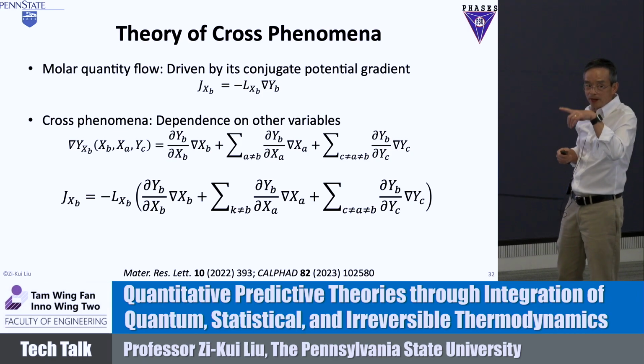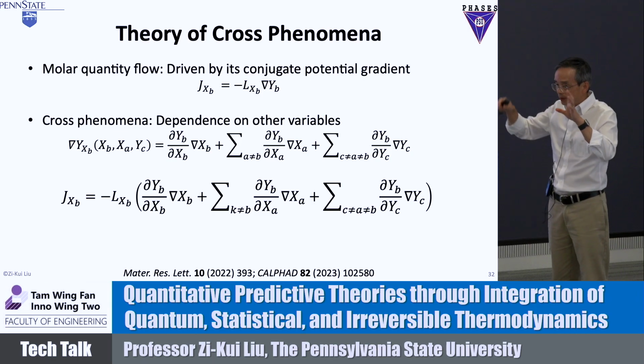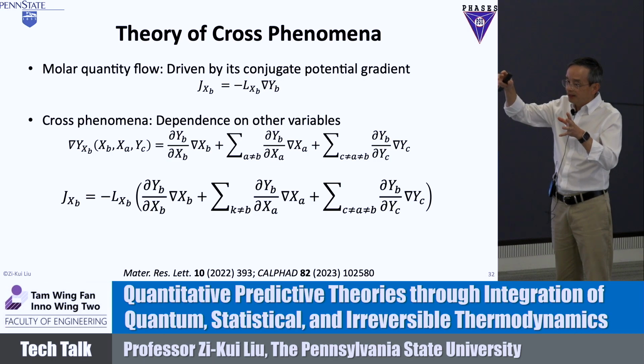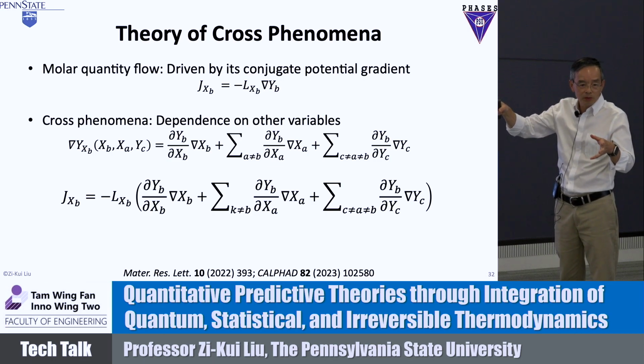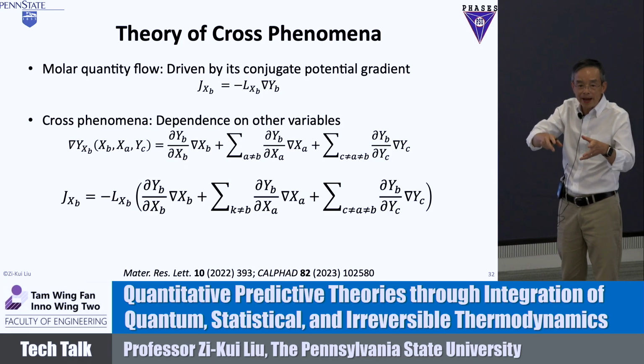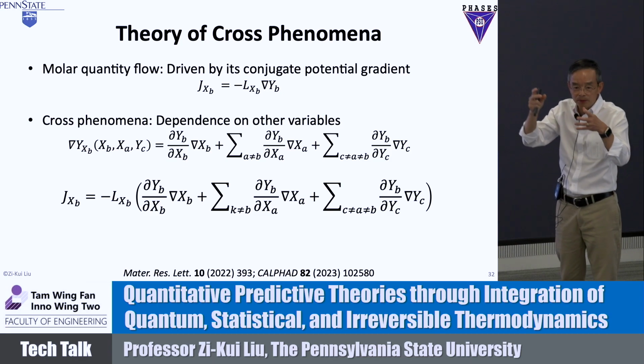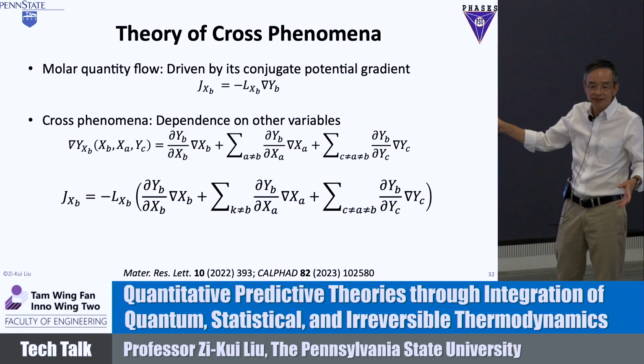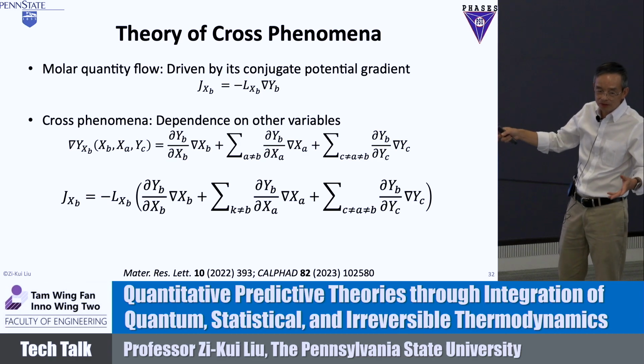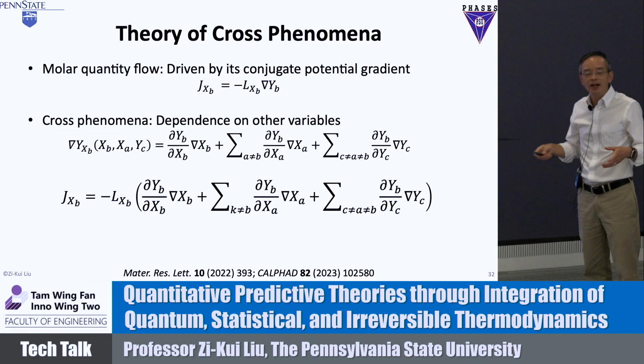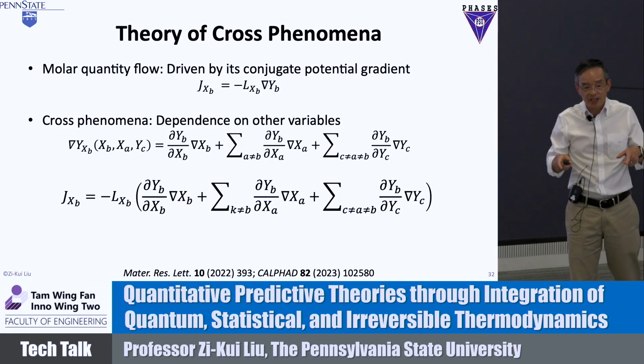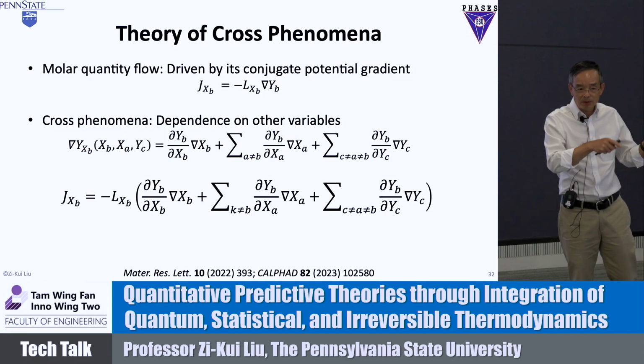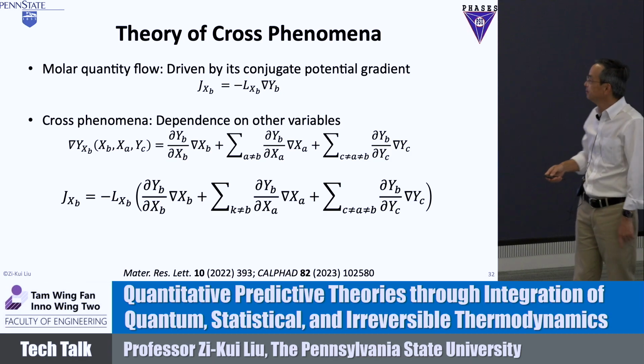Go back to some thermoelectric experiment. You add a temperature gradient, and then you do not allow the current to flow. What the system does is move the electrons to a distribution that balances your temperature gradient. It makes the chemical potential of the electron equal to 0 everywhere. There is no current flow. So it's not temperature driven, it's chemical potential driven, but the chemical potential is affected by temperature.